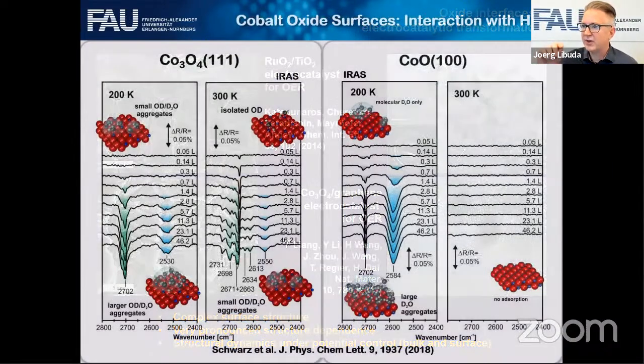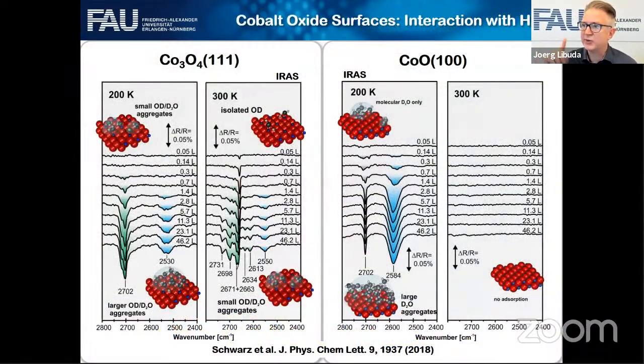So I talked about this structure dependence. I want to show you one thing, which I find totally stunning. This is a comparison. This is a surface science experiment that compares water adsorption on two cobalt oxide surfaces. It's the two cobalt oxide surfaces that I talked about before: the Co3O4(111) surface and the rock salt cobalt oxide (100) surface.